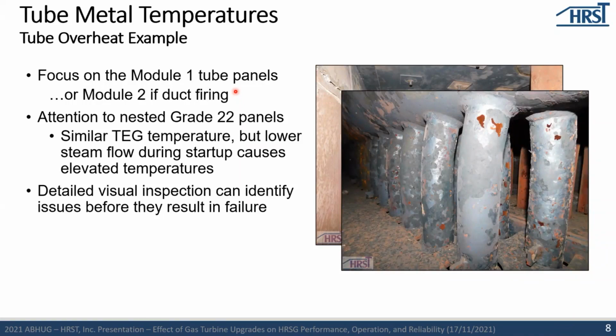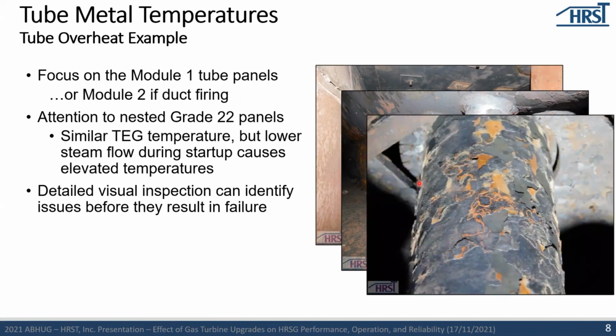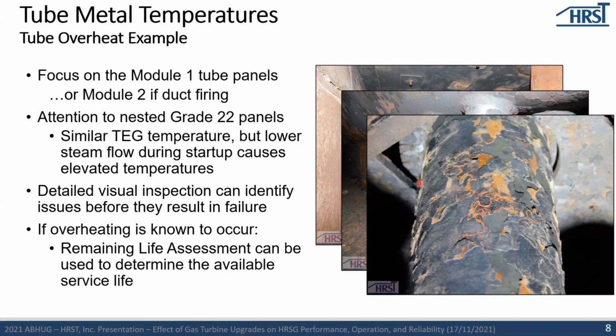You can see this exfoliation that comes about on these grade 22 tube stubs. This would be the steam outlet where you would expect the highest operating temperatures to be. And just to look at some more aggravated versions of the scaling. So if you do find notable scaling and issues like this, a remaining life assessment can be used to help determine what the used up lifespan was and what the available service life is as you move forward.